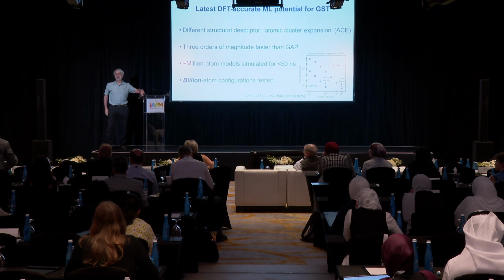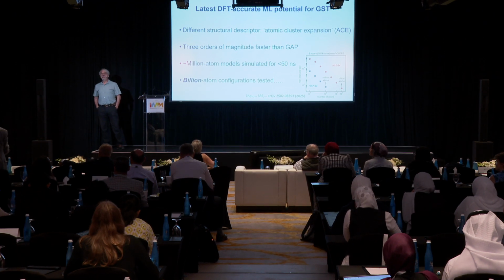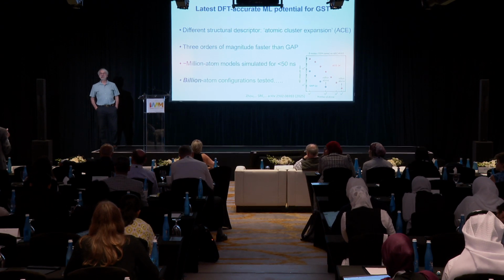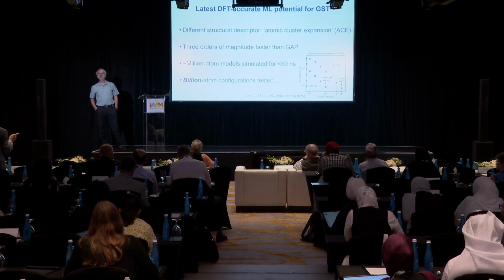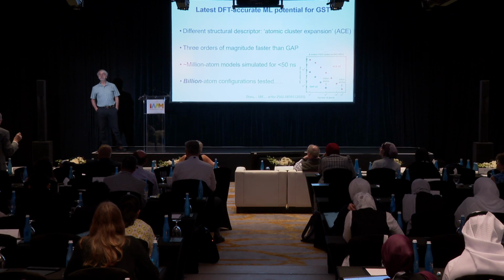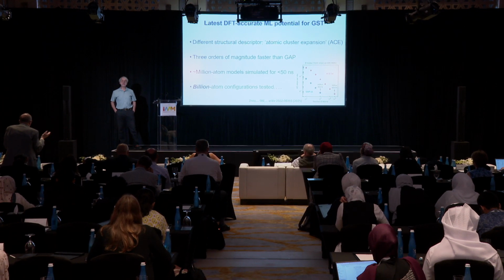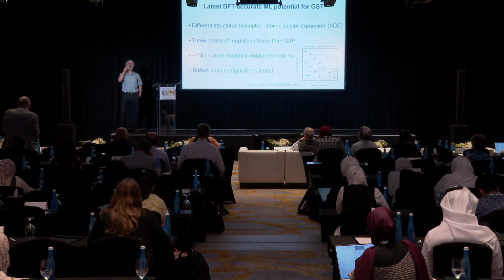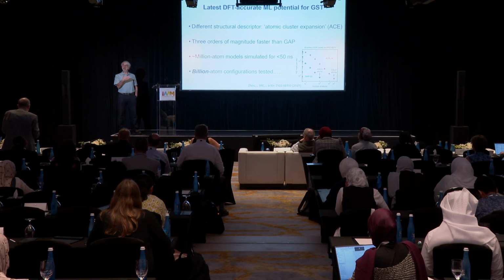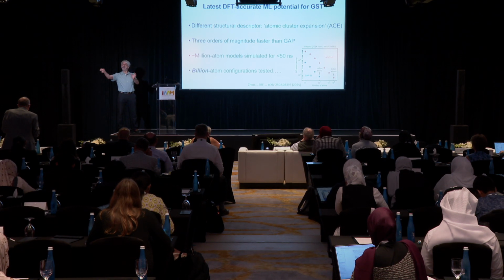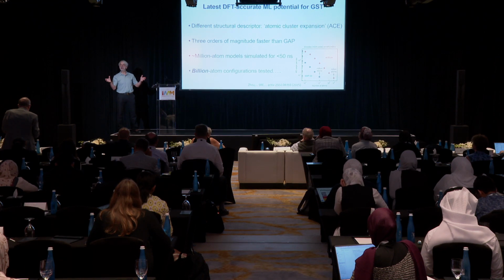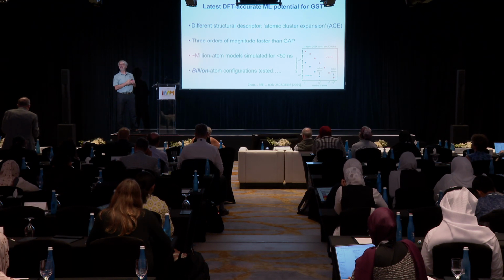Any other question? Andrew? Thanks, Stephen. Lovely talk. When you were referring to the temperature and the correlation with the switching time, is that current driven? Well, the voltage, you said a certain voltage is needed. Yeah, that's thermal. Everything's thermal. Both for the memory, it's thermal. We go from the crystal, we melt it, switch the pulse off, get to the glass, go to the crystal, you heat it, all voltage, Joule-heating. Same with the tellurium switch, just the same.